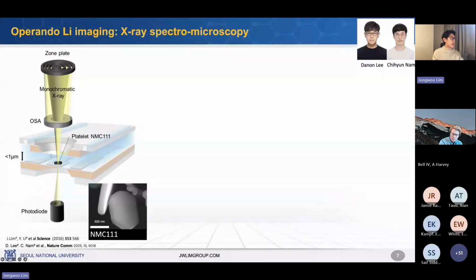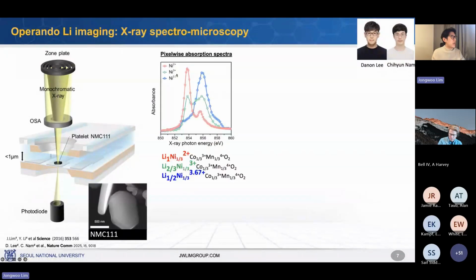And then what we do here is collect X-ray absorption spectra of the nickel. Those nickel absorption spectra are very sensitive to the nickel oxidation state. So basically we can get the oxidation state of nickel, and that corresponds to lithium concentration. For example, when the nickel is fully reduced, 2+, that means they're fully lithium rich. And when the nickel is oxidized all the way to 3.67+, that actually means the lithium is half filled, which is fully charged.